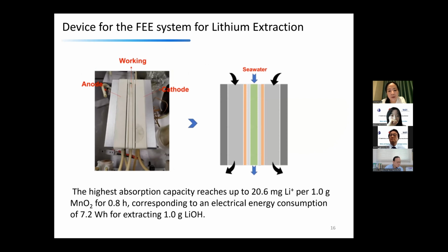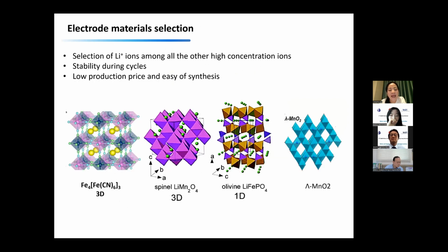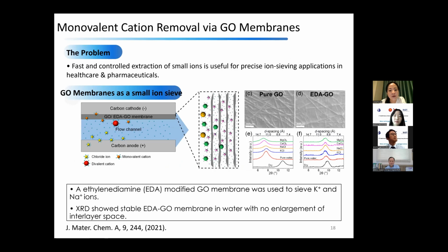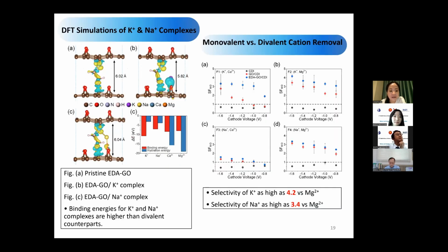So this is a working prototype we have in our lab. And these are the different electrode materials that can be utilized in this lithium recovery process. And then we have also done other monovalent cation removal through this GO membrane structure. For example, we have treated different ions like potassium and also sodium. And we can see that the different structures will have different selectivity towards potassium and sodium.